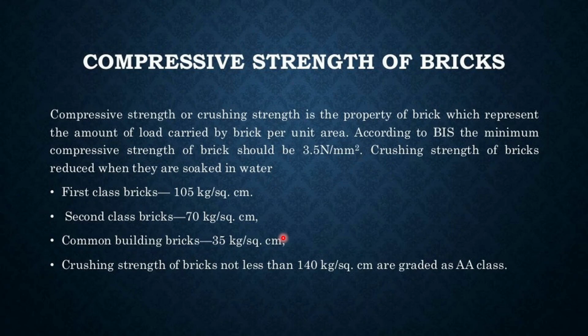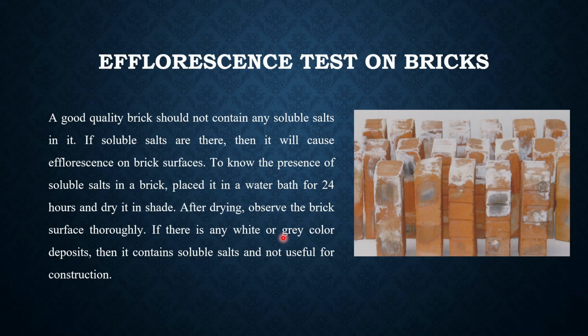And then we are going to see your efflorescence test. In the efflorescence test, we are going to find how much soluble salt is available in your brick. Usually in some cases the brick will be in very good condition, and in some cases it will have some soluble salt. How can we calculate it? After the water absorption, that means after 24 hours of soaking, you have to take the brick and keep it out. After drying, you can observe the brick completely. If you find any white or gray color deposits on the surface of the brick, that means there is soluble salt present in your bricks.